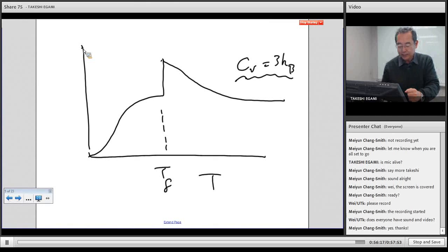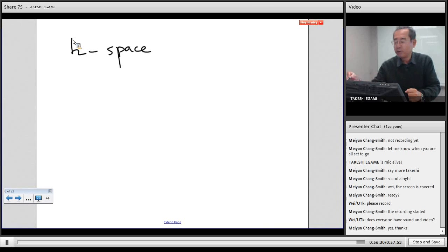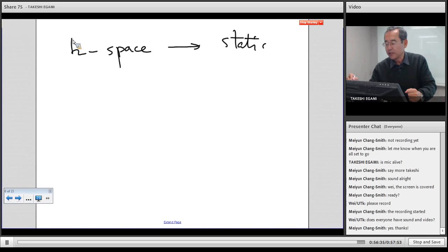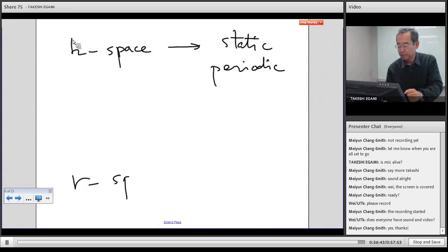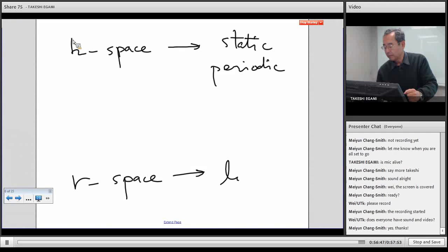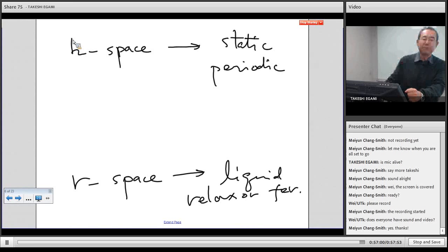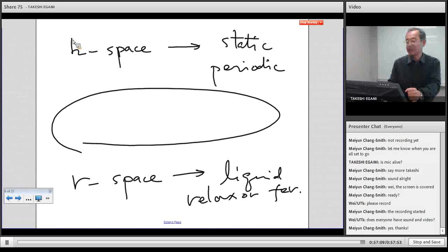So I just explained both the phonons in K-space, that is for the static phonons in periodic crystals, and real space, that's in liquid, and ferroelectric, relaxor ferroelectric, essentially like a liquid-like behavior of electric polarization. And glass is in between, so you have to use both methods to look at the different behavior. Also the strongly disordered systems are in between too. So both K-space method and R-space method are useful.